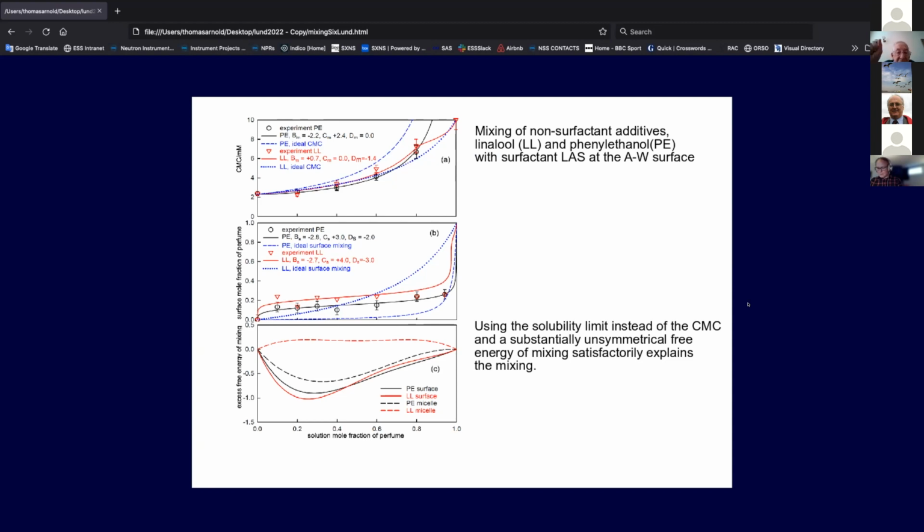And this again really occurs because there's a minimum in the free energy of the two perfumes with the surfactant at a very low concentration, not at the normal 50-50 where you'd expect it. And it's this that sustains this long absorption here. So this is another example where, again, surface tension would give you almost no information, and neutrons are supreme.